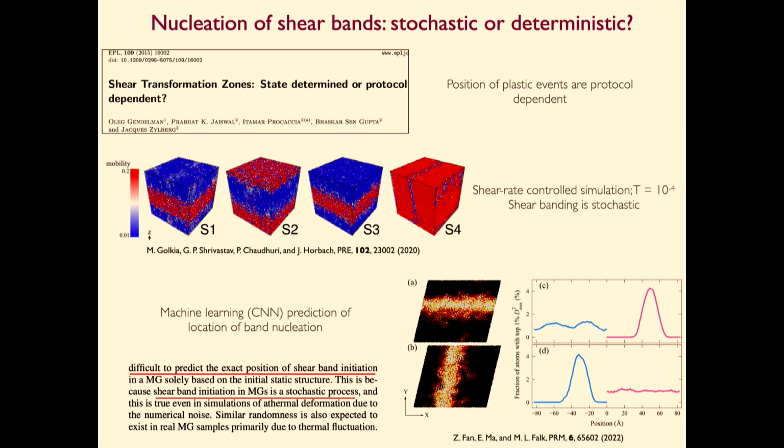So now the question is, can we predict the nucleation of such shear bands in amorphous materials? As we can see in this particular study, the first one, they tried to predict the shear transformation zones by varying the protocols, but their claim is that it is highly dependent on the protocol. If you slightly change the protocol, the nucleation of such shear bands completely changes.